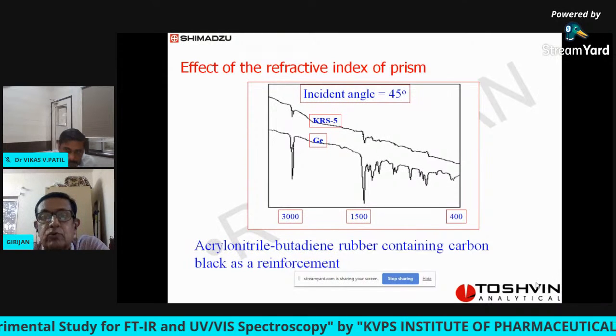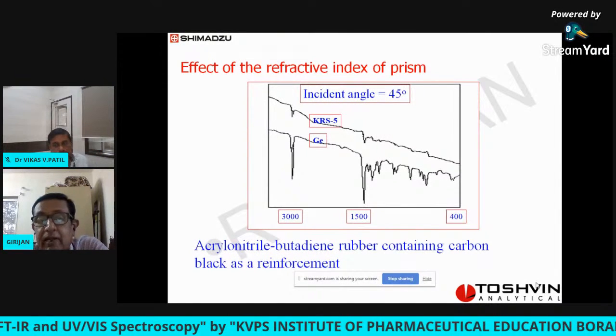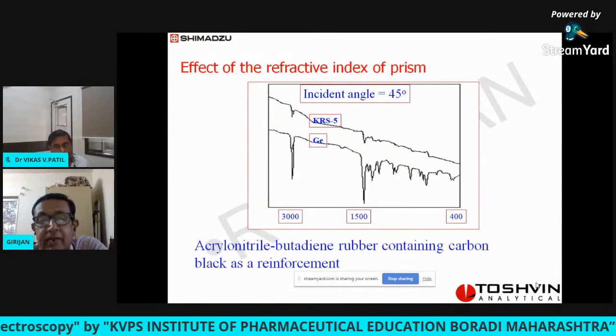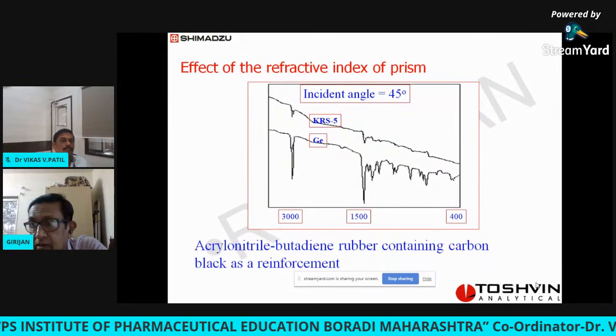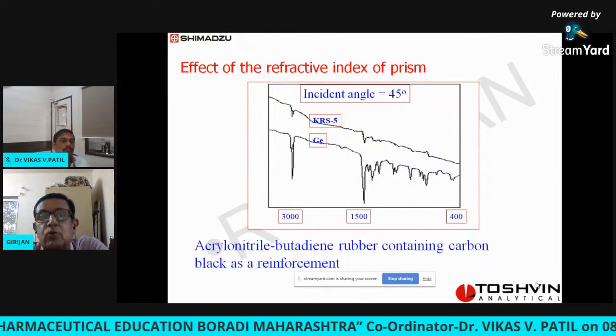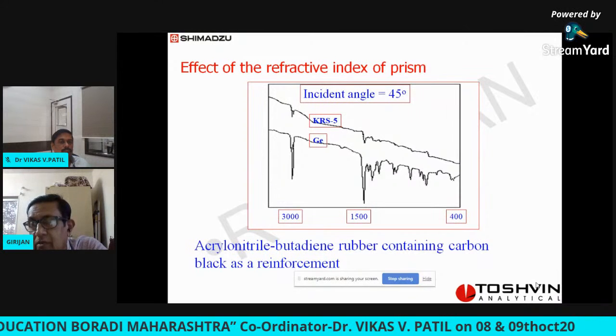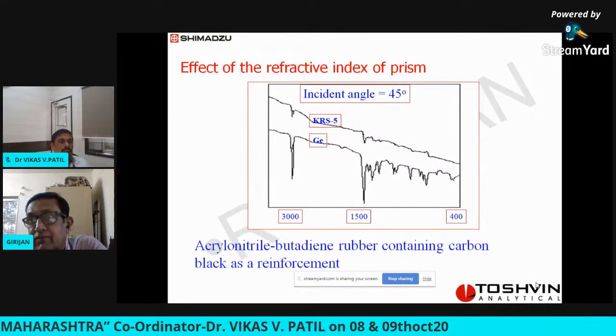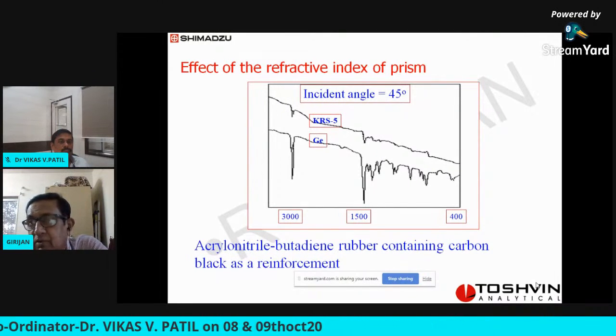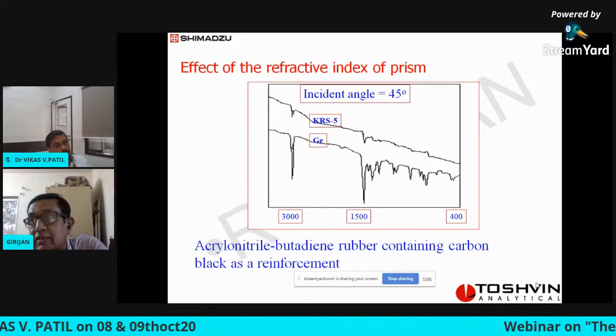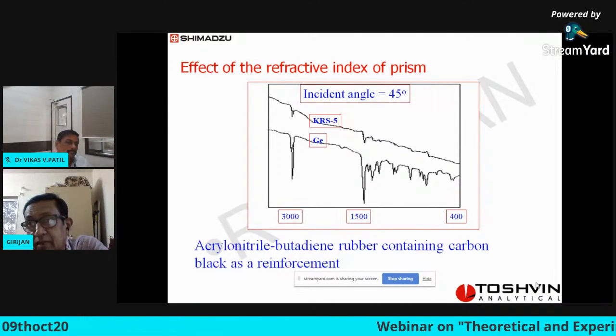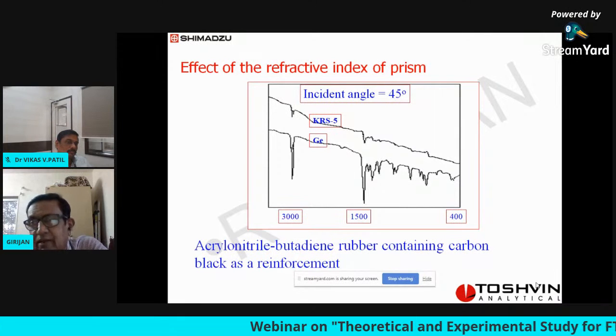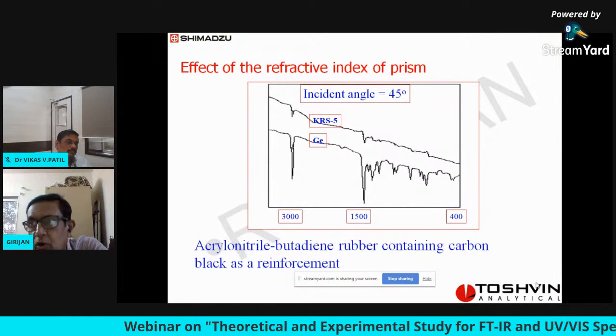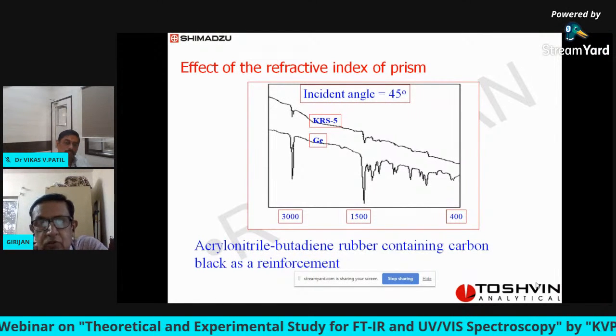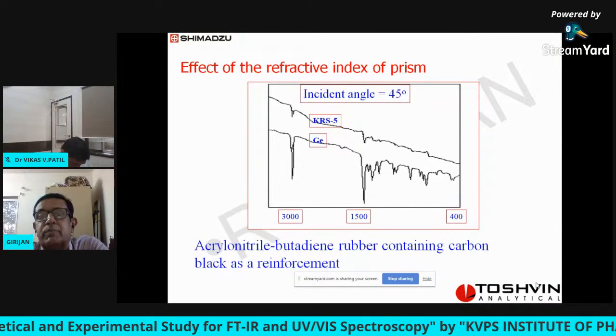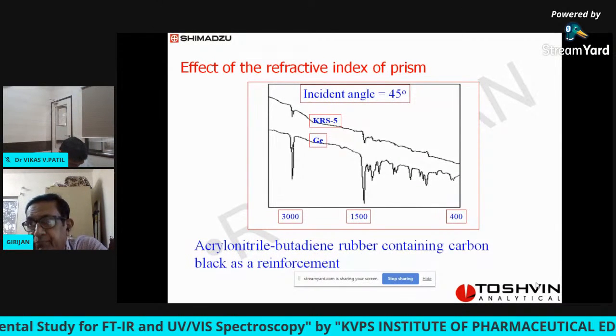Now, here we have used an acrylonitrile butadiene rubber containing carbon black as a reinforcement. We recorded the spectrum on an ATR using a KRS-5 prism. But carbon black has got a very high refractive index, somewhere around 3.5 or 3.6. And KRS-5 also has got a refractive index, I think, slightly less than that or almost very close to that. There is not a major difference between these two. So look at the spectrum. It's a very bad quality spectrum we are getting using KRS-5.